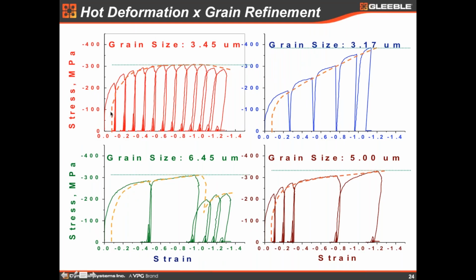We see here several passes with small deformations at constant temperature, and then fewer passes with high deformation in the beginning at high temperatures, and then lowering the temperature, increasing the stress, and having lower deformations at the end. Or we have two big deformations in the beginning and 3 small, or 3 small in the beginning and 2 big. So we can test all these crazy rolling schedules, and at the end you can get a specimen and measure the grain size. So we see that there's a big difference. This is a typical industrial deformation process. We see that we reach the smallest grain size. As opposed to this, which is not usual. Sometimes, let's say in the forging process, you may get something like that, but usually not.